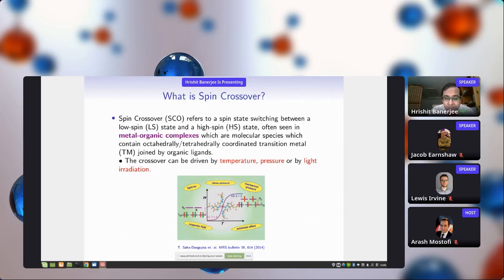That's the first question that we must ask ourselves. Spin crossover is basically a spin state switching between a low spin state and a high spin state in certain metal organic complexes, which are basically molecular species which contain octahedrally or tetrahedrally coordinated transition metal joined by organic ligands. Now, this crossover can be driven by temperature, pressure, or light irradiation, or other effects like chemical pressure or substrate effect, or various kinds of effects which change the interplay between crystal field splitting and Hund coupling. I'll come to that in a second.